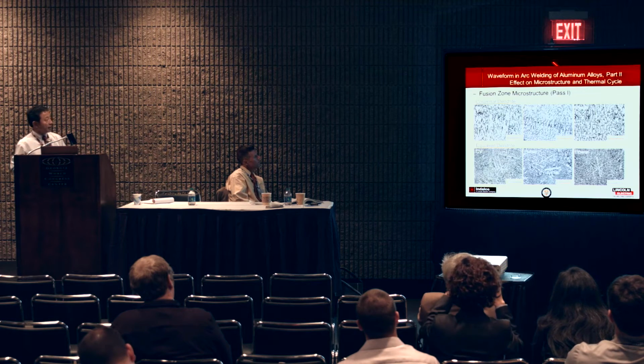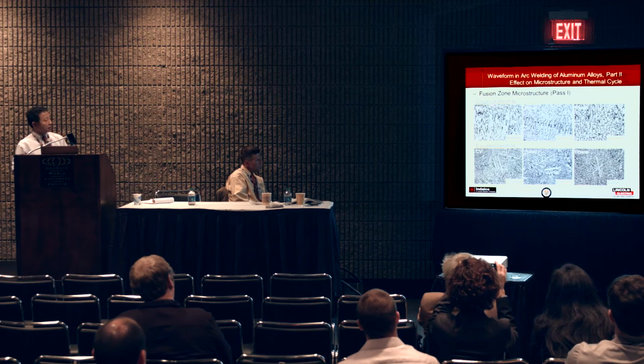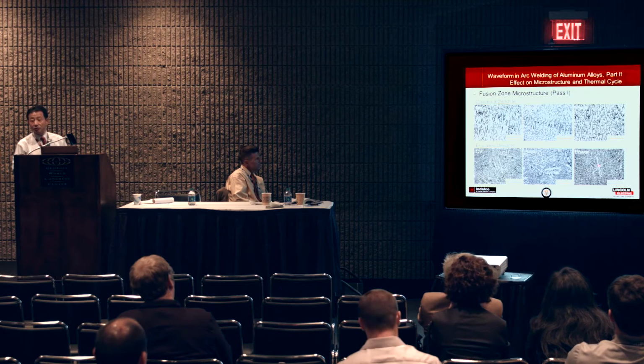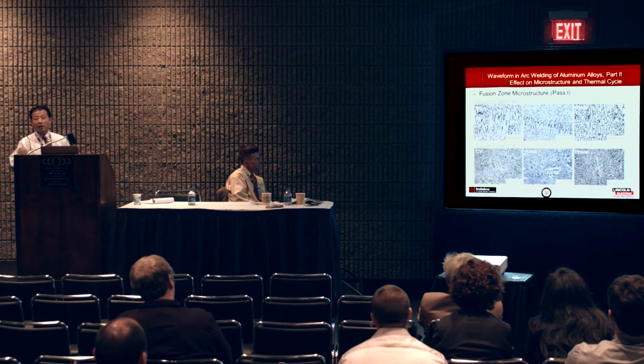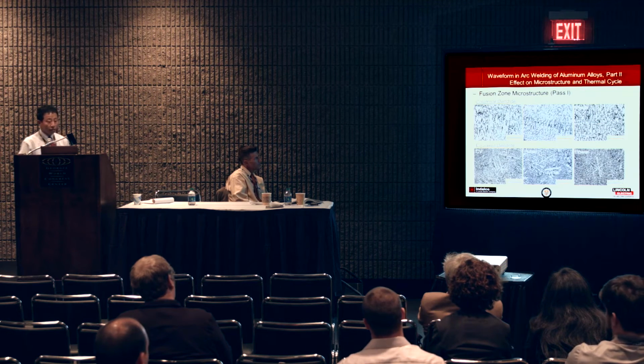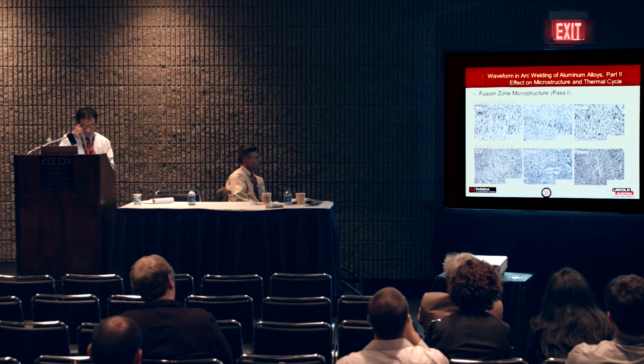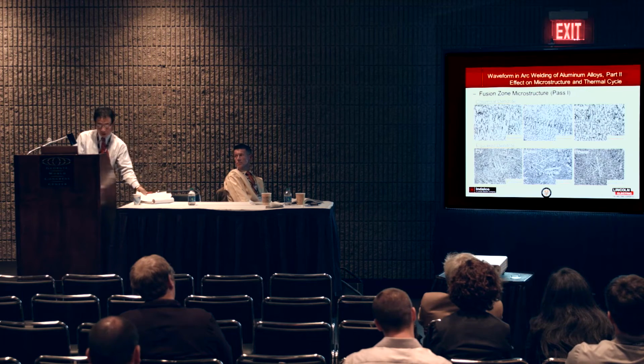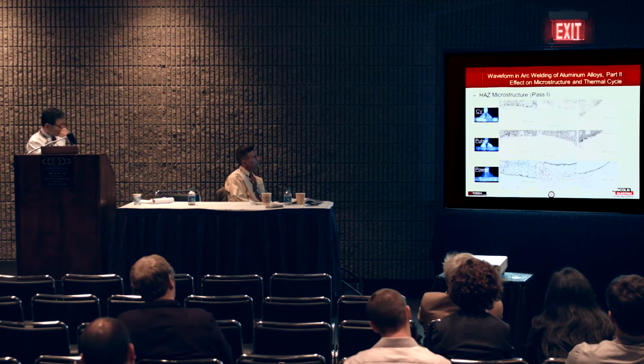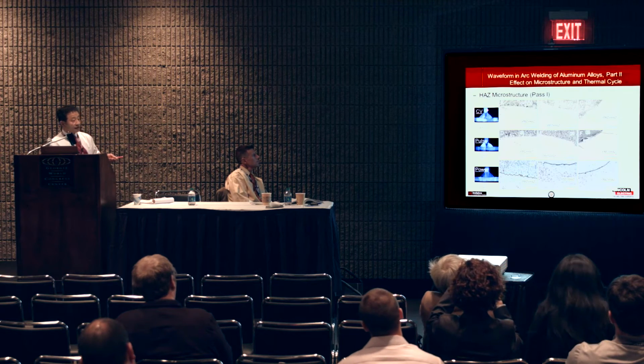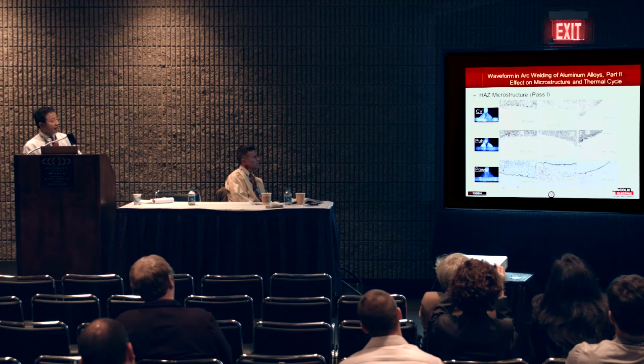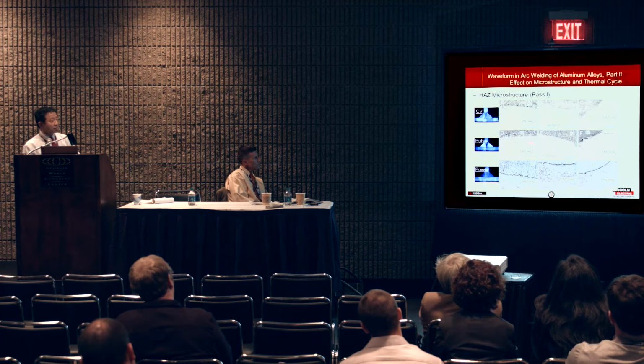I zoom in to my fusion zone, and with the columnar dendrite and my equiaxed dendrite, I show very, very good agreement. And definitely, the power mode gave me very, very fine grain structure. And also, if you look at those pictures, in my CV mode, I also detect some liquation, also with my pulse mode. And definitely, I didn't see any liquation in my power mode near my fusion boundary.